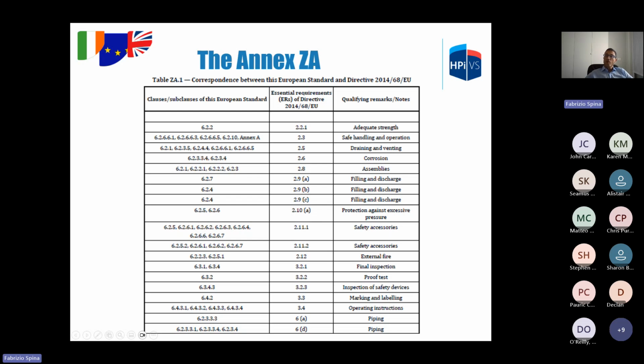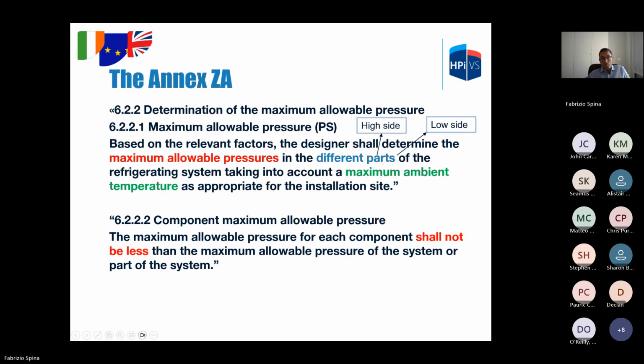Now we can start reviewing the main points of EN 378 Part 2, as outlined in the Annex ZA. So we can use this. We will evaluate all the main points listed in this annex. 6.2.2 Determination of the maximum allowable pressure. The maximum allowable pressure, PS, must be defined in the different parts of the refrigeration system, typically the high side and the low side, taking into account the maximum ambient temperature and relevant factors. Relevant factors are, for example, maximum ambient temperature, method of defrosting, solar radiation, and fouling. All these factors must be considered when defining the maximum allowable pressure of the system.